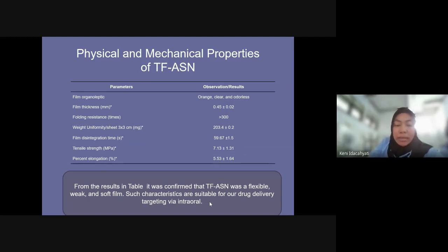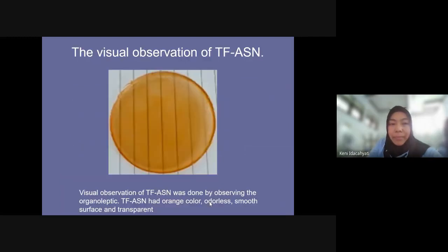From the result in the table, it was confirmed that thin film astaxanthin was a flexible, weak, and soft film. Such characteristics are suitable for our drug delivery targeting via intraoral. The visual observation of thin film astaxanthin was done by observing the organoleptic. Thin film astaxanthin had orange color, odorless, smooth surface, and transparent.